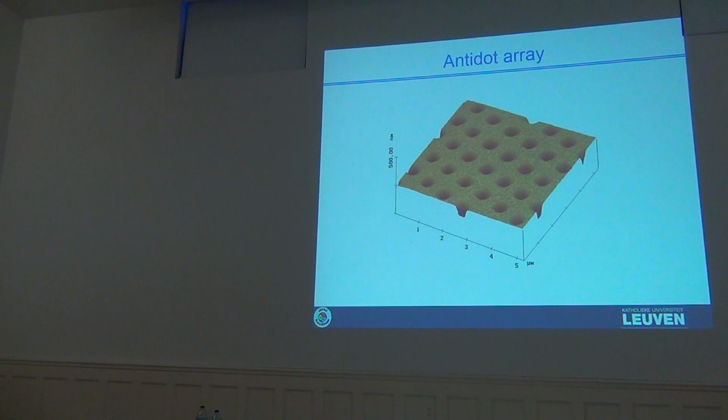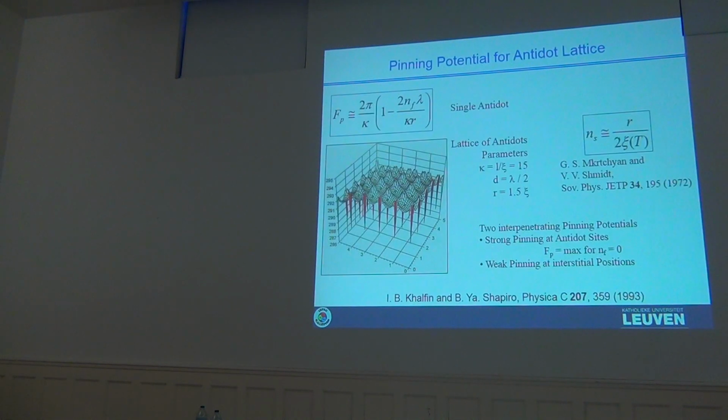Basically, I briefly mentioned in the first part that this antidot lattice we will use now to see formation of vortex-antivortex dipoles, because if you send through it a Meissner current, you know exactly the location of all pinning centers. But at the same time, it generates a very nice pinning landscape, and this makes it possible to realize experimentally this vortex Mott insulator-metal transition.